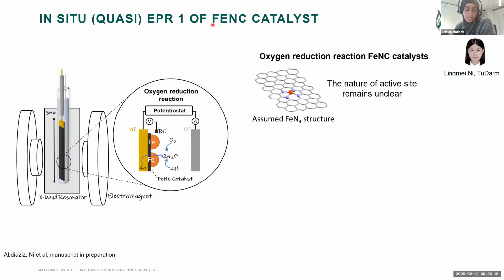In this setup, I applied it to these so-called FeNC catalysts, which are characterized by an iron with 4 nitrogens in a carbon framework. This is the assumed structure for the catalyst, but the nature of the active site is quite unclear. This catalyst is of interest to us because it's an oxygen reduction reaction catalyst, and it works similarly to the platinum that's used commercially now. However, the stability is a real issue. And so what we did was to use in situ EPR to get more information about the active site.